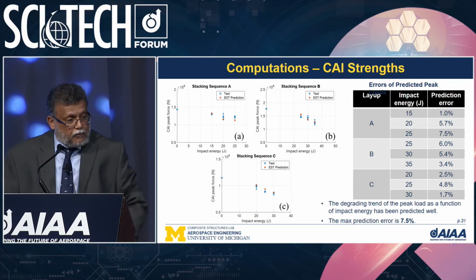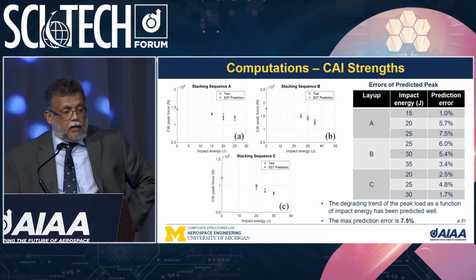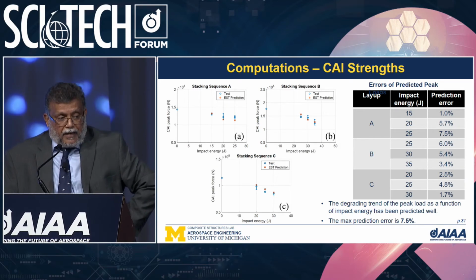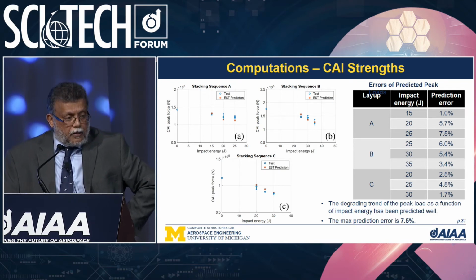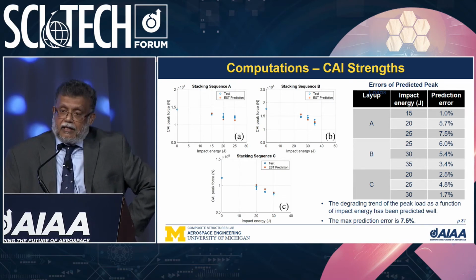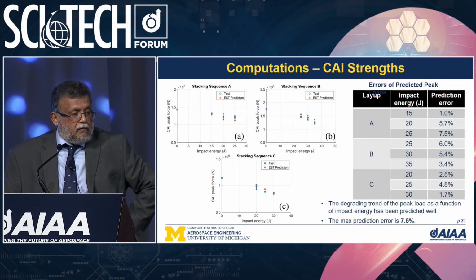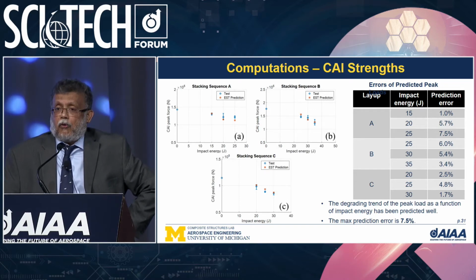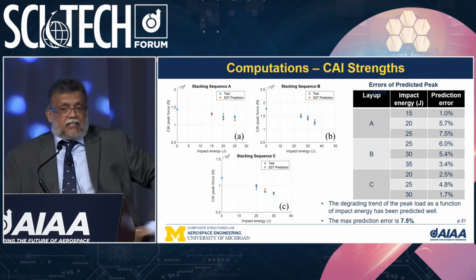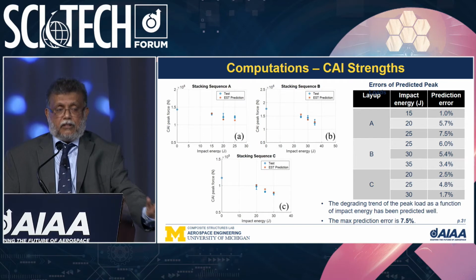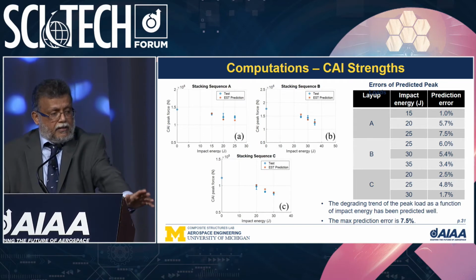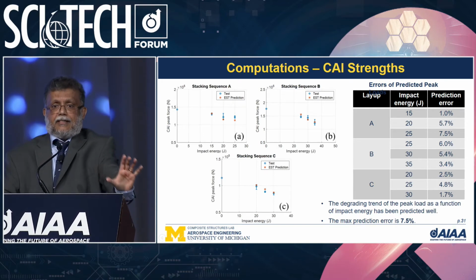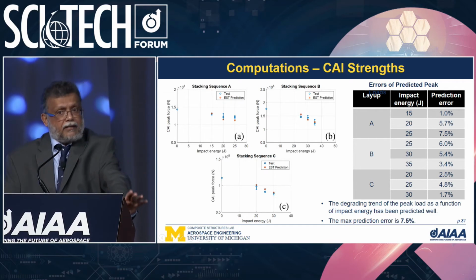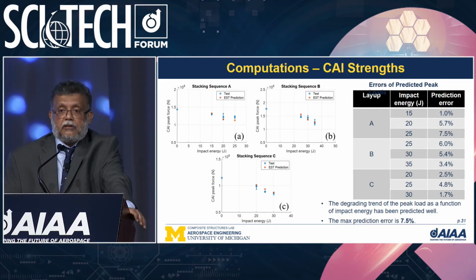You can see that for the different stacking sequences, and for different impact energies for 3 different layups, the prediction error in the strengths are within at most 7.5%, which is pretty darn good for a computational prediction, because these tests take quite a bit of resources. So we are very confident about EST as a tool to predict impact damage and to predict compression after impact.